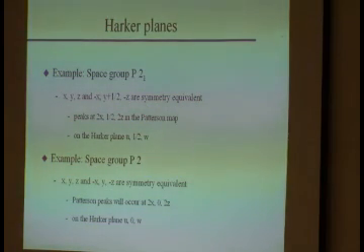Yes? So how do you get the Harker part? I understand the Patterson. How do you subtract 2? How do you get the Harker plane? You just know that? Basically, what I see here is that in my Patterson, I will have peaks at 2x, 1/2, 2z interatomic distances, okay? Which in Patterson space, I would of course call u. v is always 1/2, and w, right? Because I don't use x, y, z, because they aren't real coordinates. I use u, v, w to represent the distances.